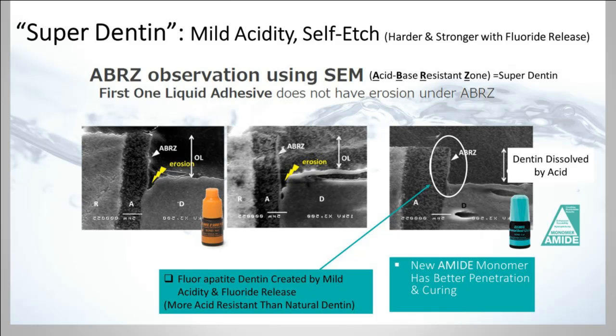He noticed on observation in a scanning electron microscope this acid-base resistance zone. You have the resin, then this zone here, and then dentin. Where the bonding agent was going in with the MDP monomers, they were seeing this zone that was resistant. This right here represents dentin dissolved by acid, but look at what happened to the acid-base resistance zone. It did nothing. He named it superdentin, because he didn't really know what to call it. It's fluorapatite dentin created by a mildly acidic, fluoride-releasing bonding agent. In the previous one, without the amide, you see this little bit of erosion when you get to the superdentin. Superdentin has always fascinated me, because once you put down the MDP and the amide monomers, you get that superdentin that doesn't dissolve in acid.